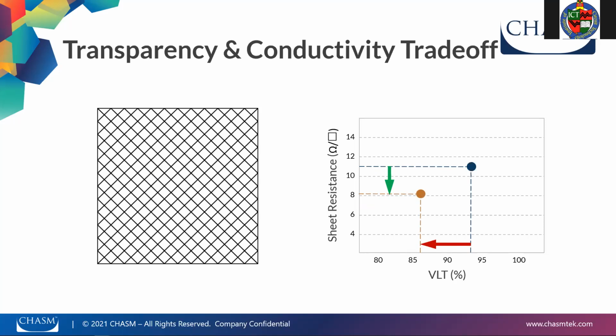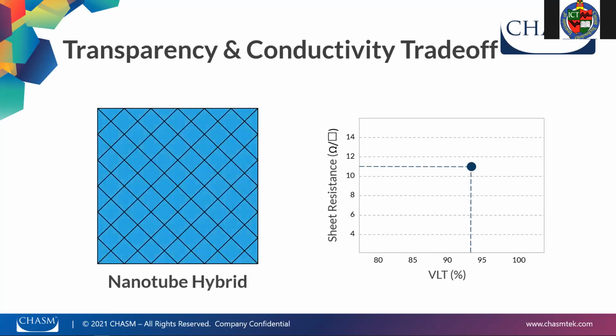So for both options of thicker conductors or more conductors, you achieve the desired goal of better sheet resistance, but at the expense of reduced transparency. So by the way, when you add fatter wires, you also increase the probability of introducing unwanted haze that happens from reflected light. So since nanotubes are conductive, the nanotube hybrid makes all the open areas of the film conductive. This means that you can actually reduce the density of the conductor and still achieve the desired increase in conductivity. The nanotube hybrid is the only category of TCF that can simultaneously increase the performance of both conductivity and transparency.